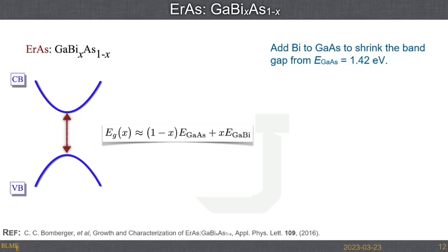So what we do with this, and this is again with Joshua Zeid at Delaware, he's been able to figure out how to grow the material, and he takes a little bit of the arsenic out and puts a little bit of bismuth into this. And so arsenic is here, and the bismuth is down here. So it's the same chemical valence, but it's a heavier element here. And specifically, the spin orbit coupling of the material is quite a bit larger with all of this. So it's a change in the electronic properties because of the change in the mass here. There's just simply more of it there. It puts strain on the material. And there's also a change in terms of how the electrons couple to magnetic fields.